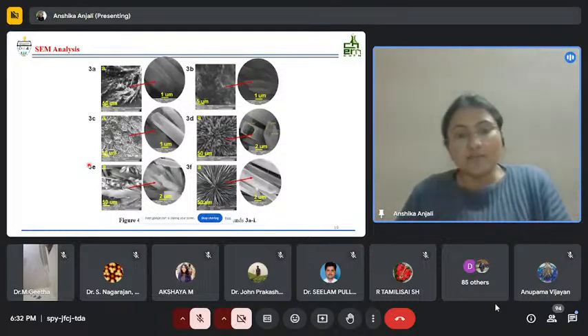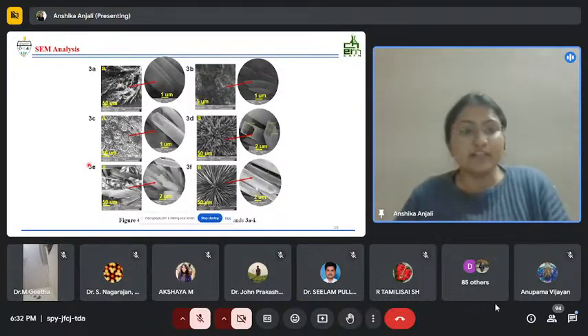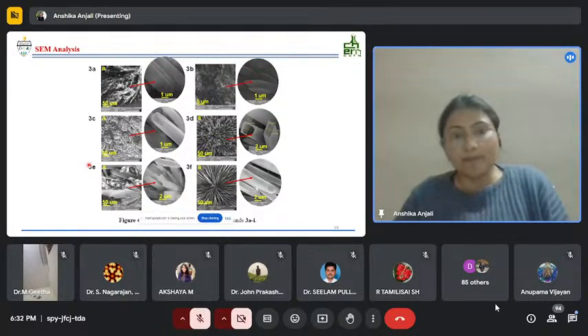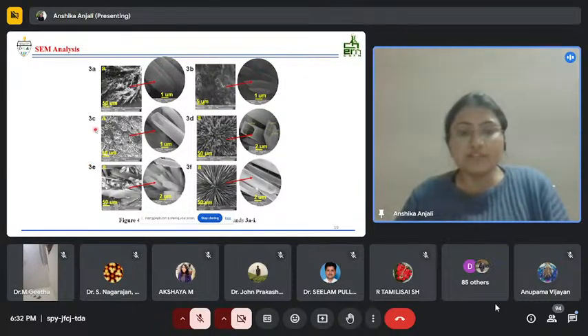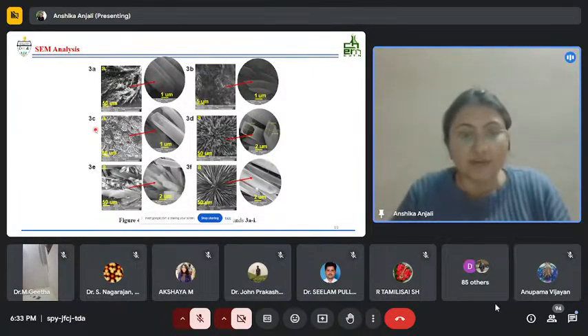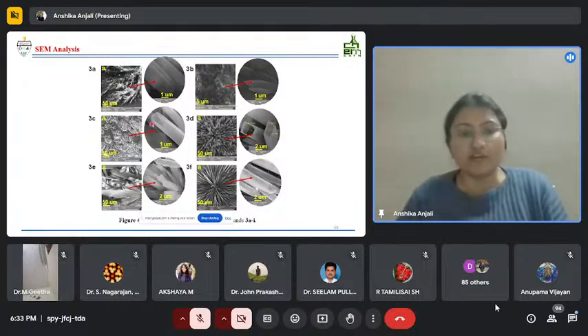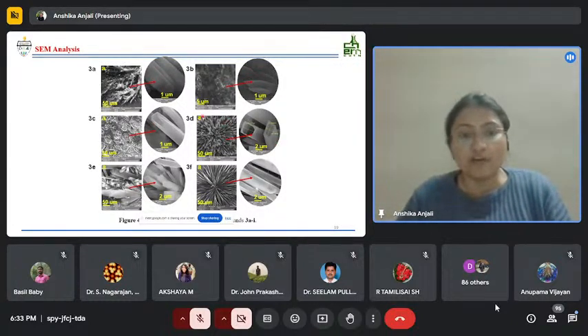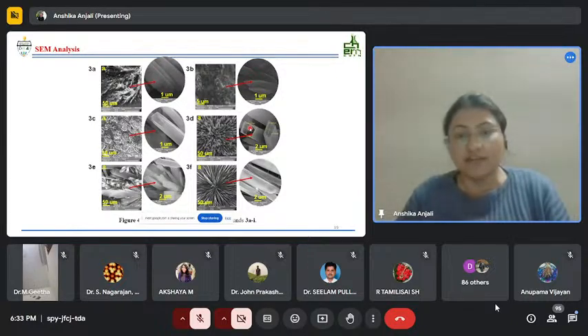When these compounds were fabricated into thin films and the surface morphological studies were done using scanning electron microscopy, the presence of different end groups resulted in versatile morphology. As we can see, we got a flower-like arrangement. Then some rectangular rods were also observed.